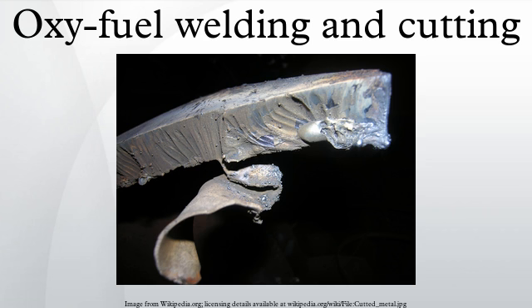The welder must also keep the filler metal in the hot outer flame zone when not adding it to the puddle to protect filler metal from oxidation. Do not let the welding flame burn off the filler metal. The metal will not wet into the base metal and will look like a series of cold dots on the base metal. There is very little strength in a cold weld. When the filler metal is properly added to the molten puddle, the resulting weld will be stronger than the original base metal.